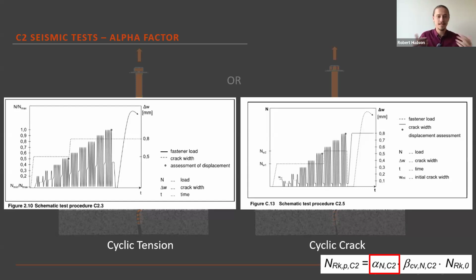Overwhelmingly, the reason that our C2 capacities are so much lower than what we used to use is because of the cyclic crack test. And this is the test that C1 doesn't take into account, which is why C1 capacities are significantly higher.